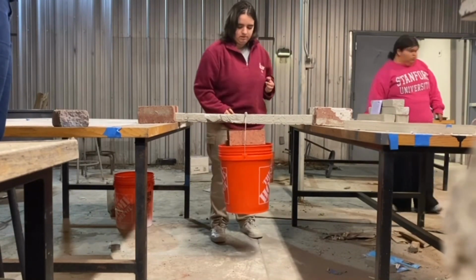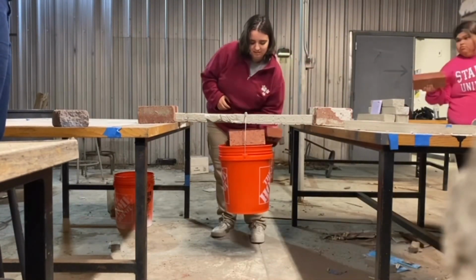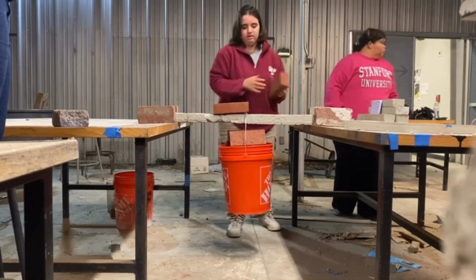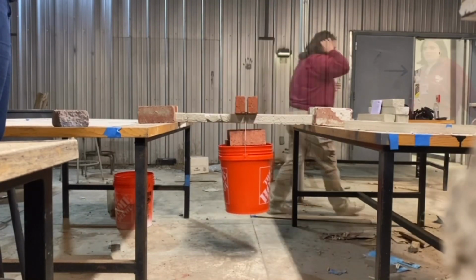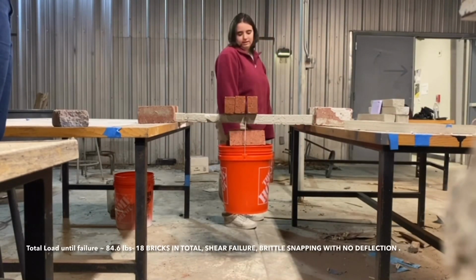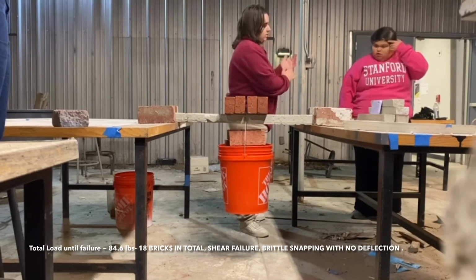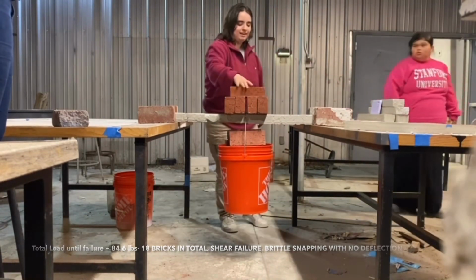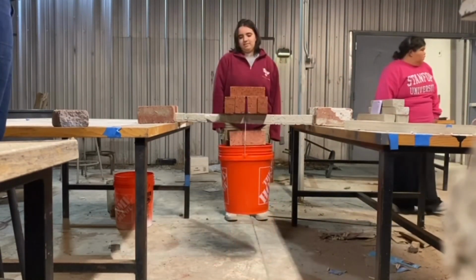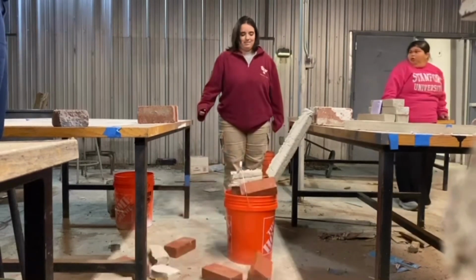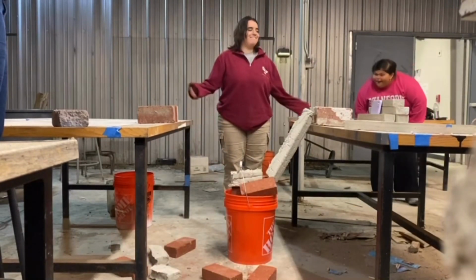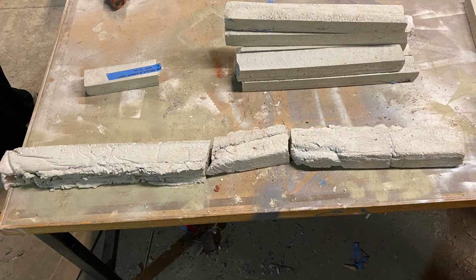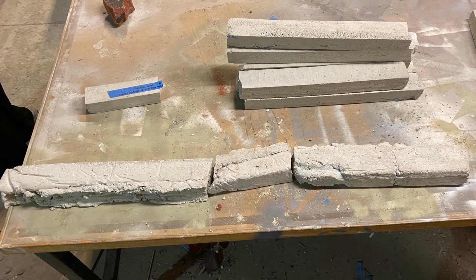Due to the beam being non-reinforced with any tensile material, the beam starts to crack in between the point load and the end of the beam. The unreinforced beam undergoes a shear compression failure and snaps. When the brittle beam hits the floor, it breaks again. Due to a lack of any wire or mesh, the beam broke into multiple parts in a brittle state.